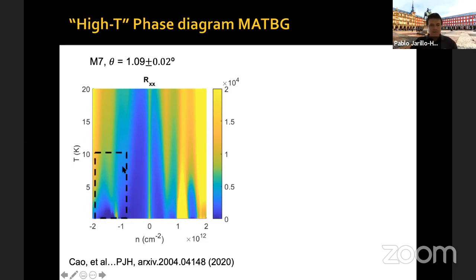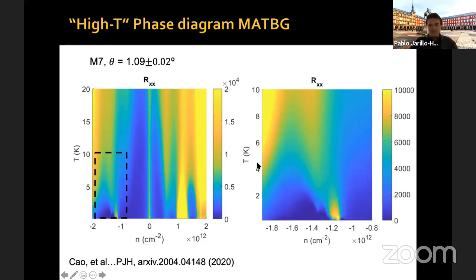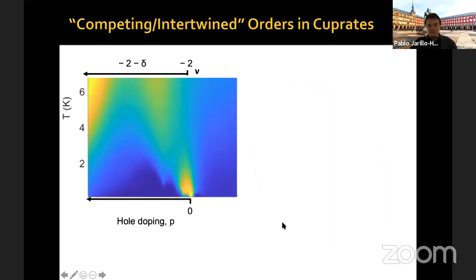Now, let me zoom in a little bit more in this region here. So in this region, this is 2 holes per moiré unit cell. It has a weak but present correlated insulating state. And then there is this high temperature feature. We call it sometimes the banana ridge, but it's this resistance wedge, this ridge here. And the dark blue is actually the superconducting dome.